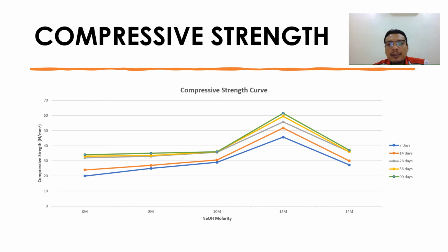Based on the result, the compressive strength of concrete is increased when molarities of sodium hydroxide increase until 12 molarity. However, the compressive strength of the concrete decreases when the molarity of sodium hydroxide exceeds 12 molarity. The optimum compressive strength 61.5 Newton per millimeter square was seen at 12 molarity of sodium hydroxide compared to the control 34 Newton per millimeter square at 90 days.